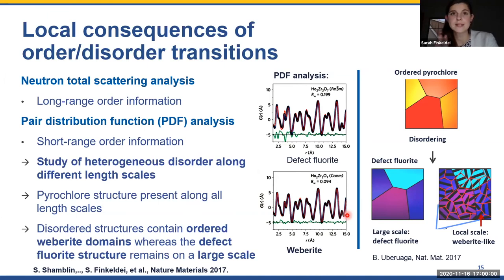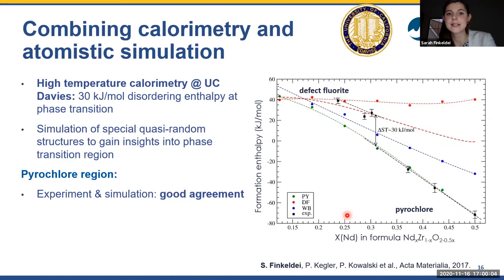And then we went one step further and also studied the formation enthalpy of this ordered structure, the pyrochlore, to the disordered defect fluorite structure with calorimetry, and described it also with computational models.